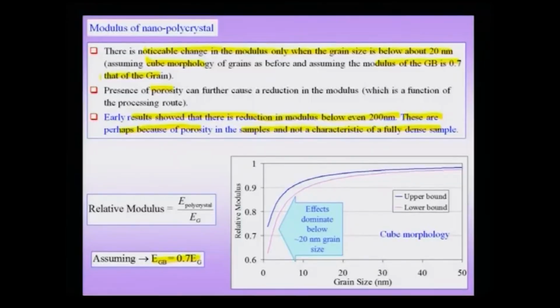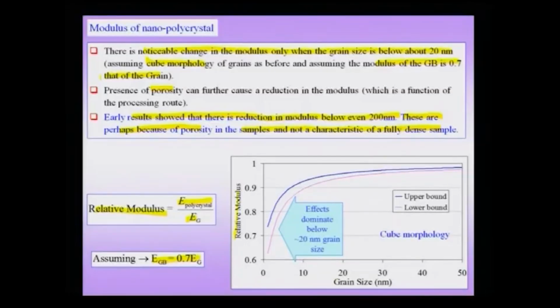And if I use the value of E GB as 0.7 E G, and I have a relative modulus defined as E polycrystal by E grain, that means the reduction in modulus with respect to that of a grain, and I plot the relative modulus with respect to grain size, I see that most of the changes seem to take place when you are around 20 nanometers or below. So, this seems to be the region where these other entities actually play an important role, and there is a reduction in modulus.